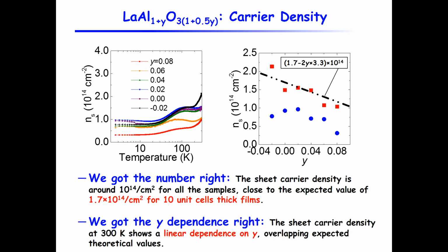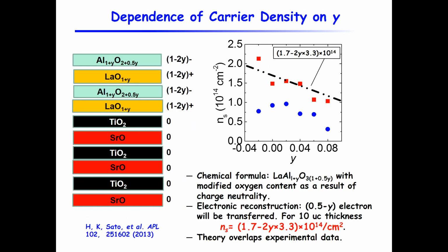The dependence on the stoichiometry is because when you have different stoichiometry, the charge carried by each layer is different. Instead of plus minus 1, it becomes plus minus (1 minus 2y). And so the amount of charge they transfer to the interface depends on the stoichiometry of lanthanum aluminate. This is what you would expect, and these are the data points that we observed at room temperature.